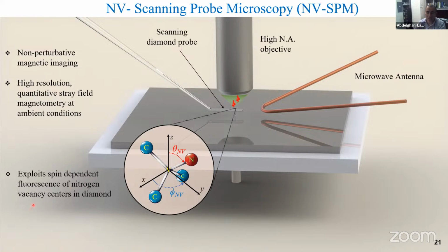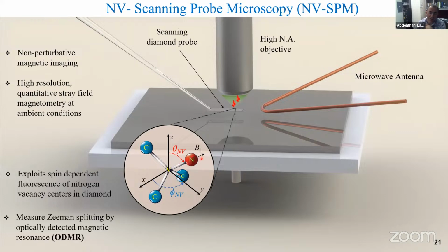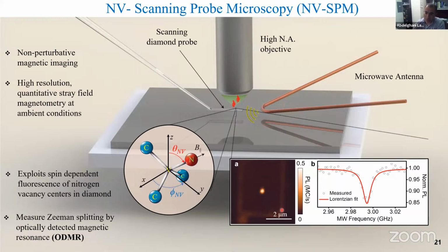Now if you apply a magnetic field along this direction of the NV axis, you can measure the Zeeman splitting by this ODMR, as I showed before. In this ODMR, we have a microwave antenna to excite this spin state just for readout. Here I show the optical image of a single NV in a nanopillar. Here I don't show the two peaks, just one of the ODMR transitions of this spin state. By looking at the shift of these transitions, one can measure the external signal from the spin textures. That's how the detection works.